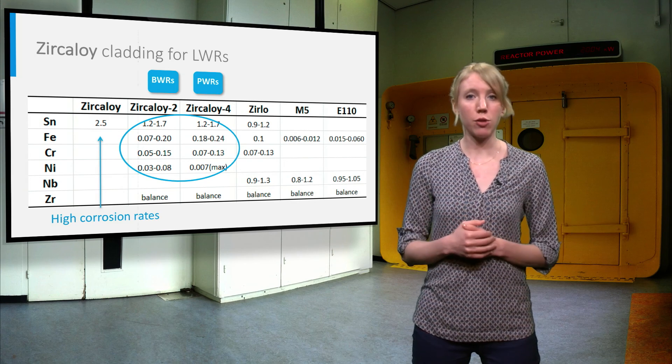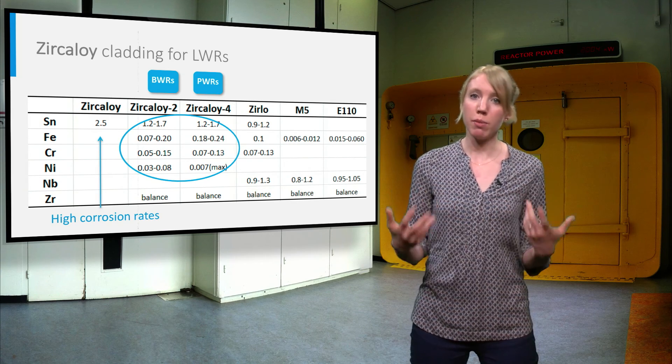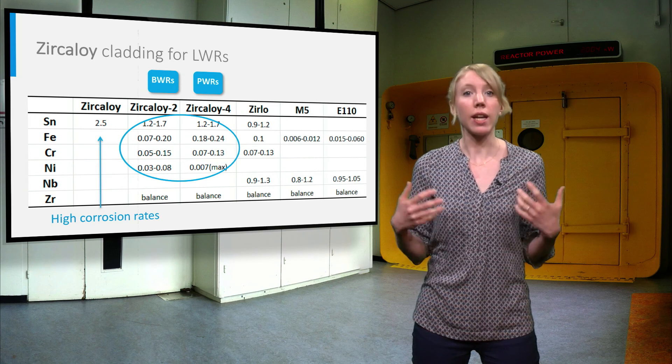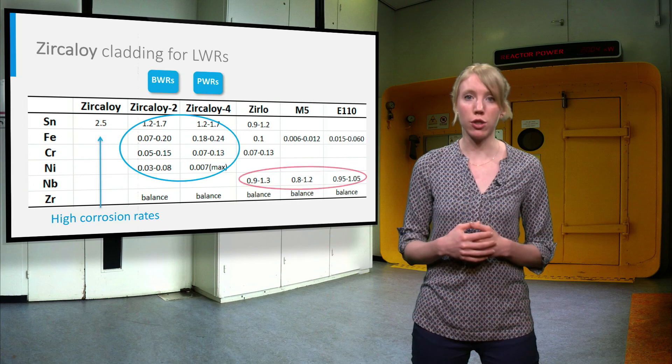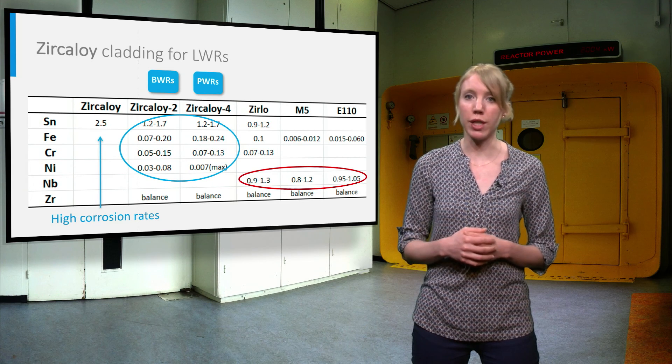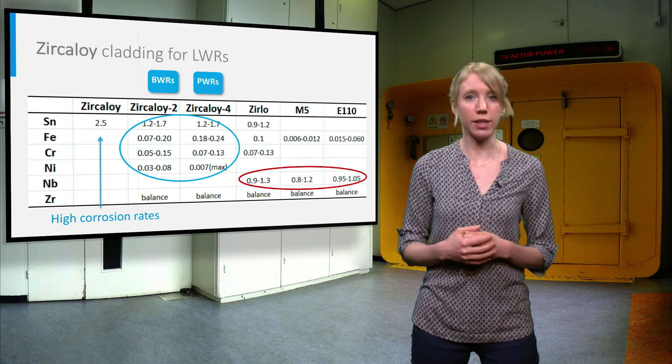With the increasing target burn-up of the fuel, the demands on the corrosion resistance have increased further. And nowadays, alloys of zirconium with niobium have been introduced under the commercial names ZIRLO, M5, or E110.